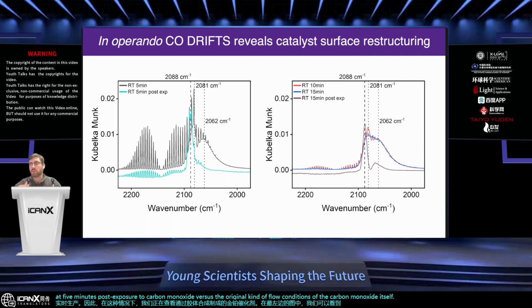So here what we see is we get a narrowing of the vibrational features, which are actually indicative of the carbon monoxide binding to the platinum atoms that are stuck on the surface. And depending on the concentration of those platinum atoms and whether they're right next to each other and we have a bridging carbon monoxide, or we just have an end-on carbon monoxide, this technique is going to allow us to see and understand that.